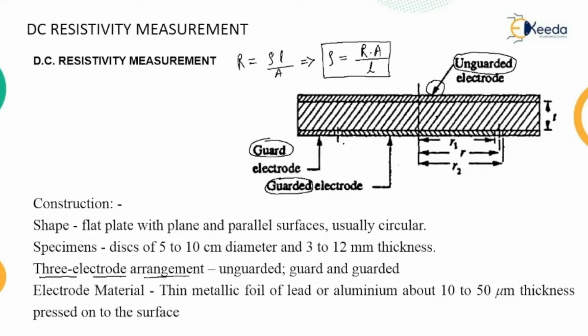The effective diameter of the guarded electrode is greater than the actual diameter and is given as follows. The dimensions are shown here in the form of radii R1, R, and R2. Let R1 and R2 be the radii of the guarded electrode and guard electrode, including the gap, and R the effective radius of the guarded electrode. Let the gap width be G and the specimen thickness be T. So this is your unguarded electrode, guard electrode, and guarded electrode, and in between them a specimen of thickness T is placed.